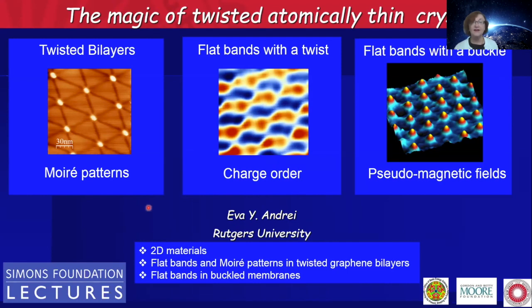So what I'm going to tell you today is about two such examples. Both actually involve graphene, which is a one atom thick crystal of carbon. And in both cases, what we're going to be after is so-called flat bands. Now, flat bands is a case where the kinetic energy of the electrons is quenched, and as a result, the interactions between them become important, and they're able to create a coherent macroscopic state where they move in lockstep and give rise to interesting phenomena such as superconductivity, charge density wave, magnetism, and so on.